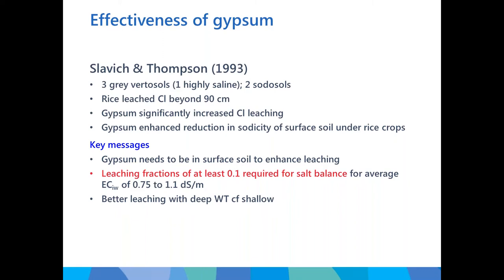So putting that gypsum on prior to freshwater events or a leaching event will facilitate leaching of salts, and it will also help you shift the sodium that's in the profile. It needs to be in the surface before the event. That other point there will make sense later on. Leaching fractions need to be at least 0.1 for a salt balance. If your irrigation water EC is 0.75 to 1.1. Now, 1.1 decisiemens is not particularly salty.